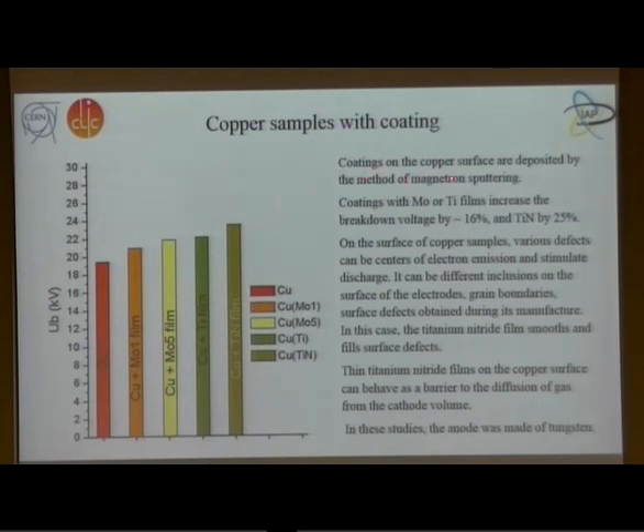The coating on the copper surface was deposited by the method of magnetron sputtering. Coating with molybdenum or titanium films increases the breakdown voltage by 16%, and titanium nitride by 25%. On the surface of copper samples, various defects can be centers of electron emission and stimulate discharge.